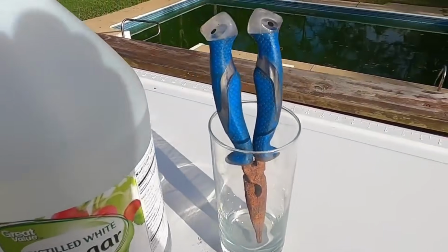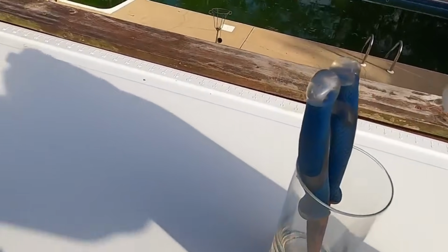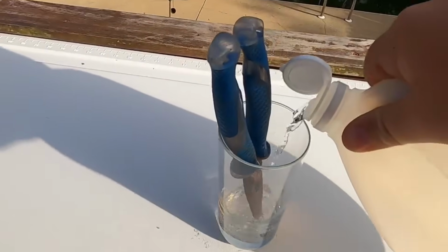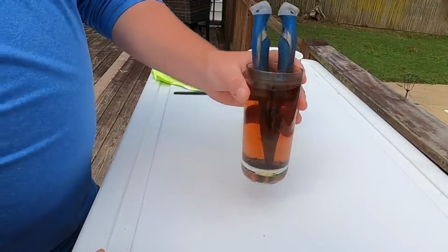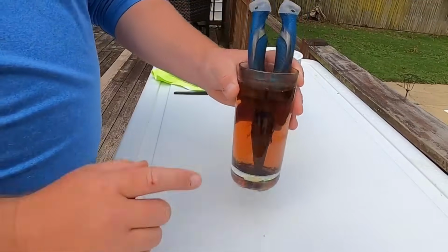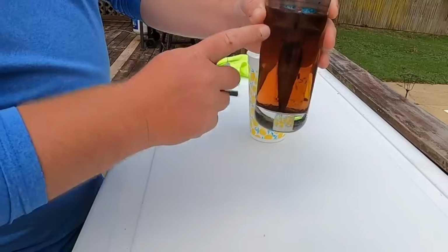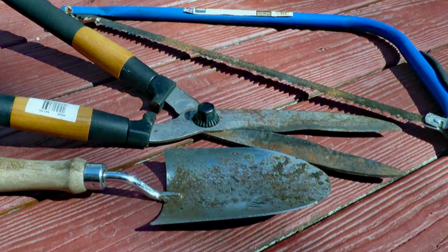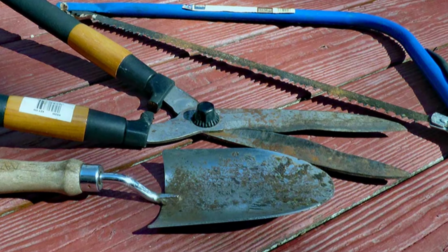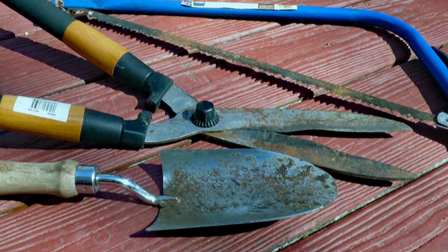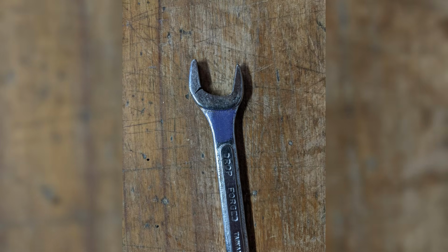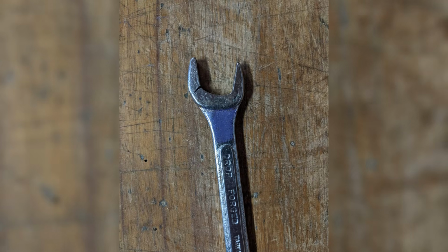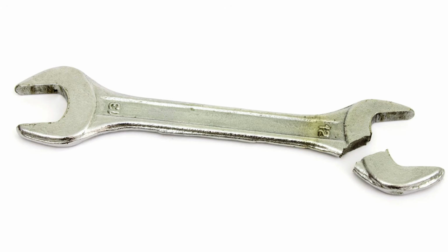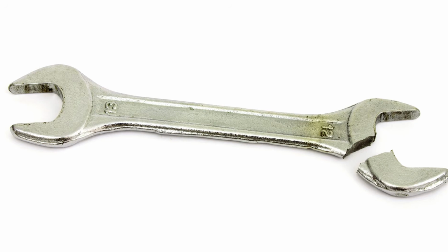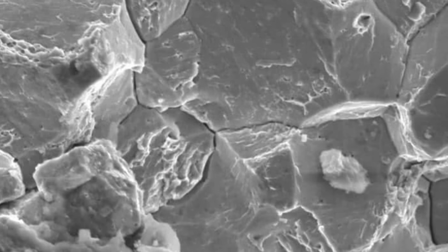Because of its extraordinarily small atomic radius, that hydrogen diffuses directly into the crystal lattice of the steel. It migrates toward areas of internal stress, grain boundaries, microscopic defects, and there it combines into molecular hydrogen gas. That gas cannot escape. It builds internal pressure. It expands microscopic voids into micro cracks. The tool looks fine. It feels fine. You put it back in the drawer, and then 3 months later, you apply normal torque to a fastener, well within the tool's rated limit, and the wrench snaps. Clean fracture, no warning. That is hydrogen embrittlement, and it is irreversible.